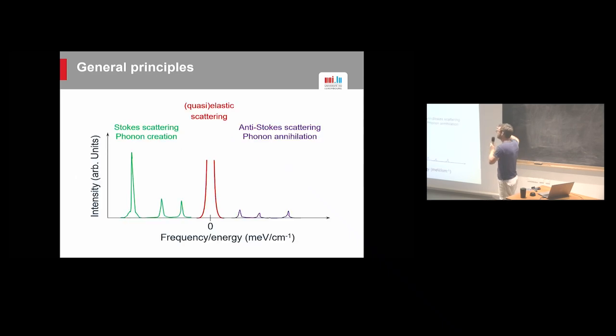But again, at the end of the day, whichever technique you're looking at, the spectrum that you're going to measure is something like that. So you're going to have some elastic or quasi-elastic scattering at the middle, and then you're going to have two sides with your excitations or your phonons, the energy gain side, so the anti-Stokes, and the energy loss side, okay, the Stokes scattering. So those two sides are symmetric in the sense that the position of those peaks is just the energy of your phonon. So this doesn't depend on the process. The intensity is not, because then temperature comes into play.